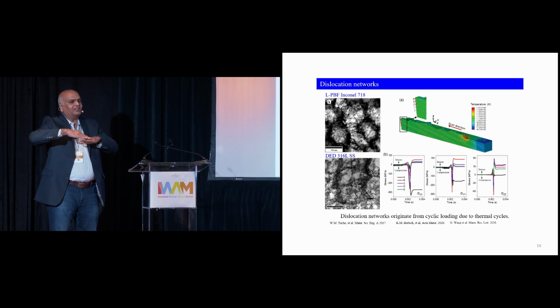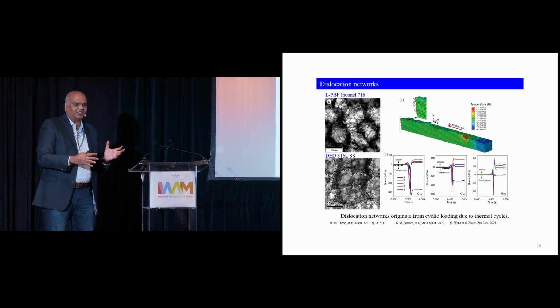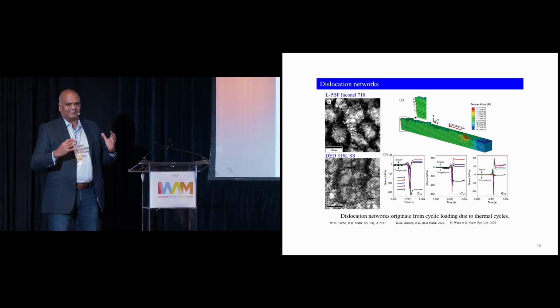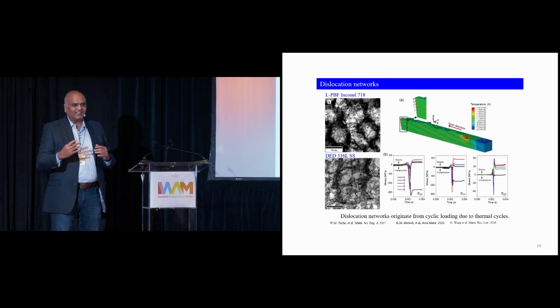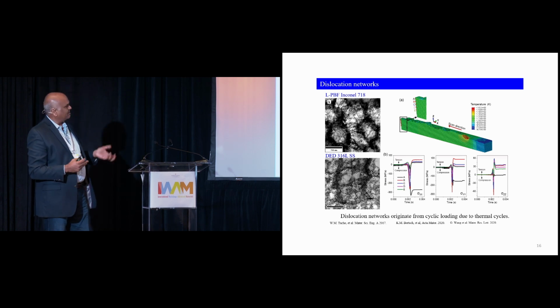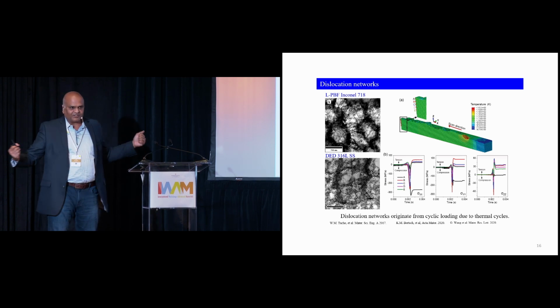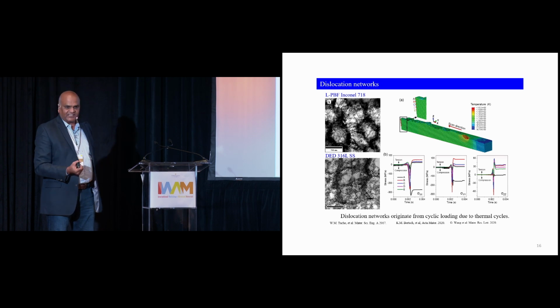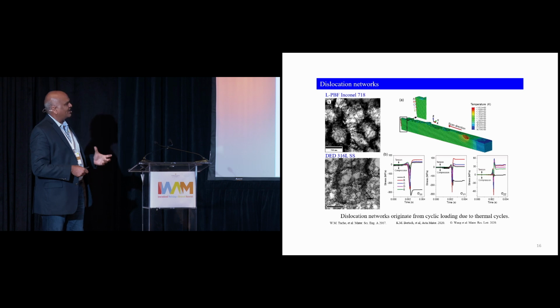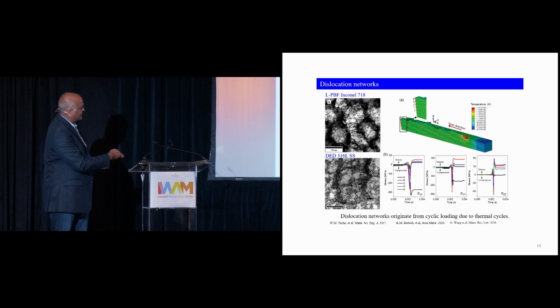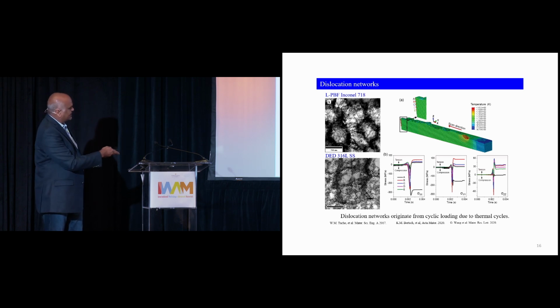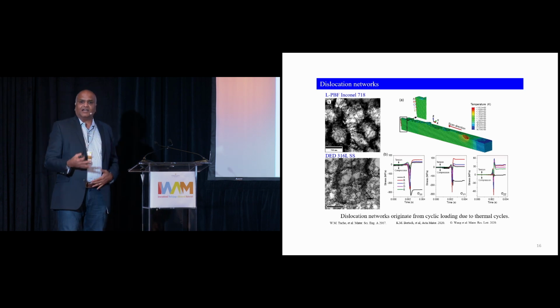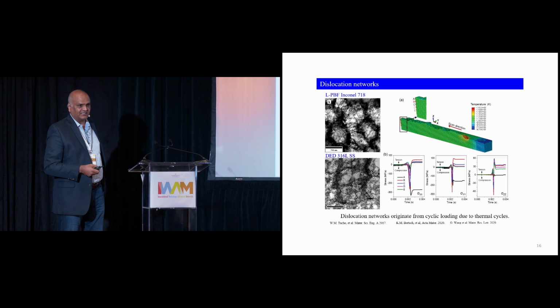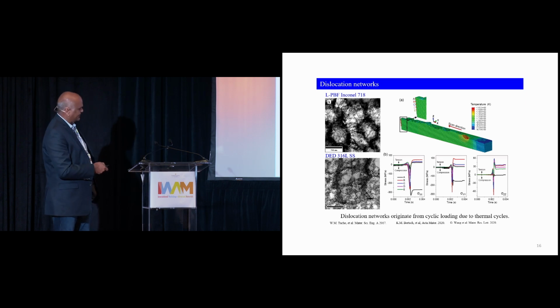In conventional manufactured metal, this doesn't happen - it's all cooled at the same time. Here, you're repeatedly heating and cooling it, and because of that there is quite a lot of stretching and contraction. It's like fatigue, not conventional fatigue as you think of it, and as a result, as these simulations show, there are fairly substantial thermal cycles, so you have fairly large dislocation debris accumulating, and these dislocations decorate the cell walls.